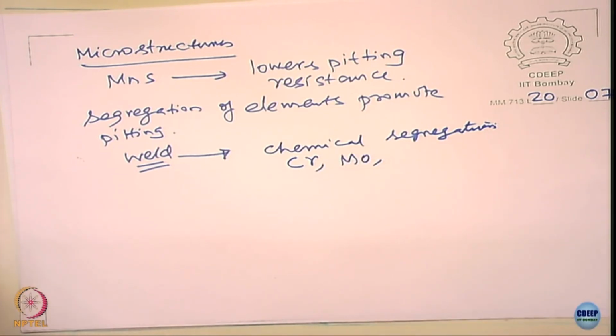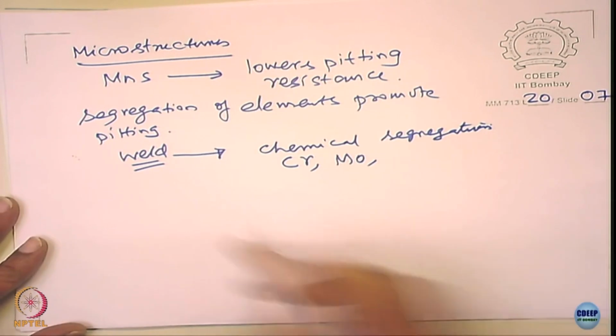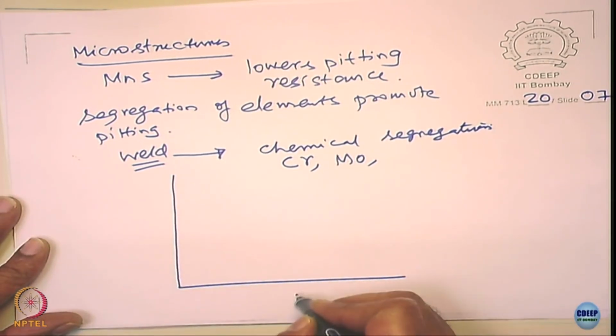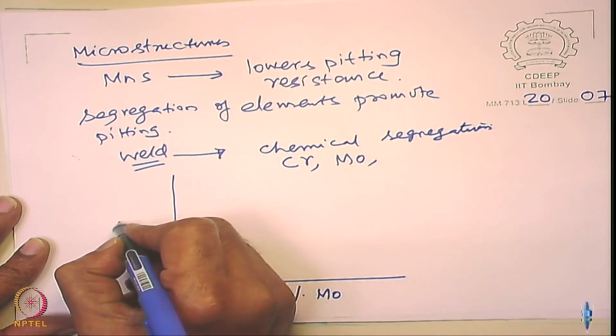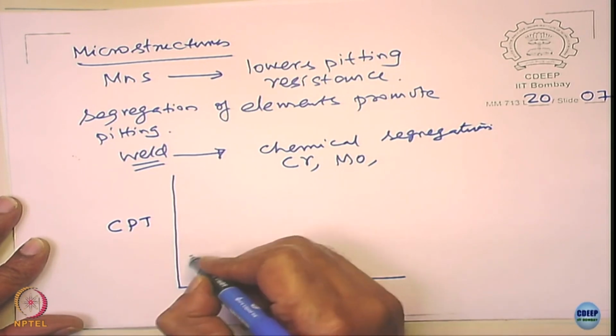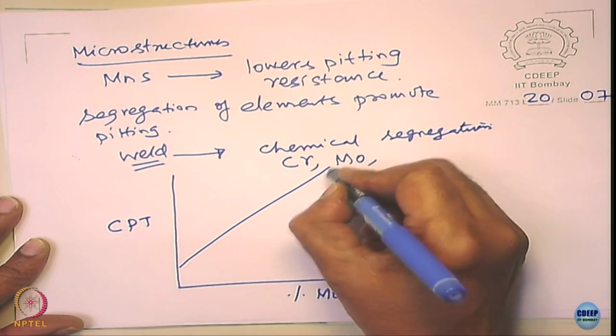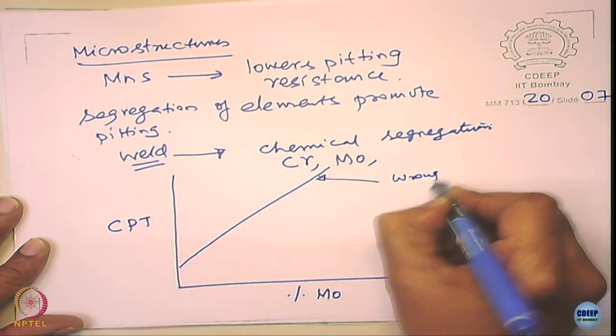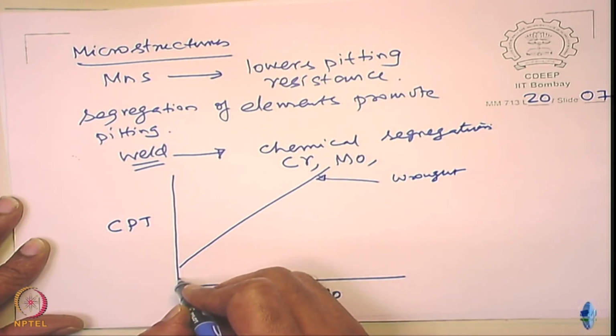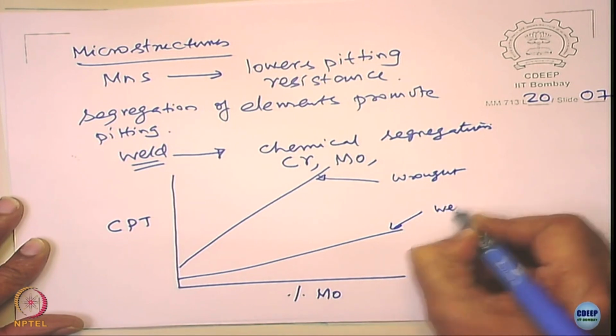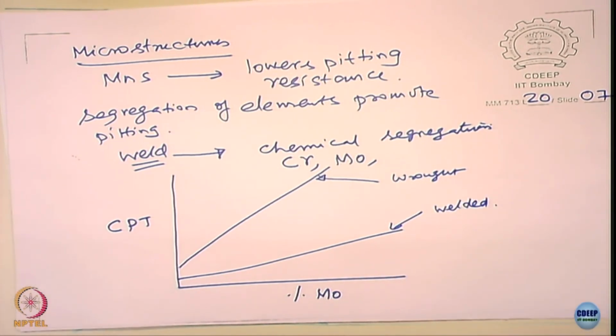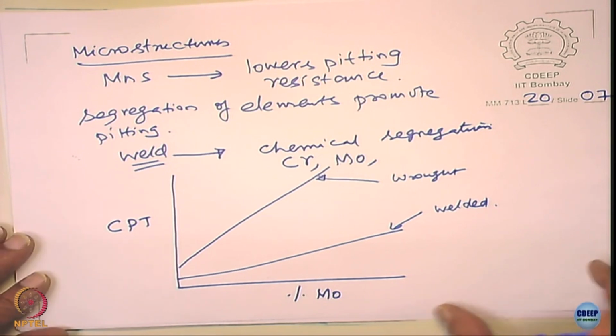So, you have some place which is enriched with the chromium, some place it is depleted with the chromium. What will happen to pitting resistance? The pitting resistance will fall because there are some regions poor in chromium content, moly content. In fact, if you look at some of the literature published, if you see the percentage of molybdenum versus the critical pitting temperature, normally the critical pitting temperature goes like that. It is the wrought and it is welded. What happens? Welded. I will tell you later what is critical pitting temperature. So, the microstructures play a role because microstructure leads to different chemical variations,